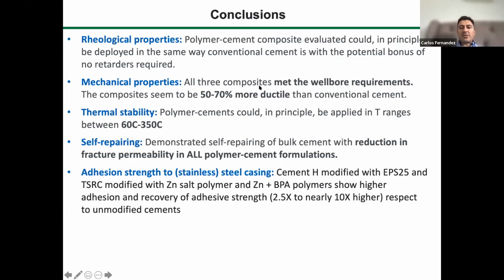Mechanical properties: the compressive strength is reduced, but still above the wellbore requirements. It's about 50 to 70% more ductile, and that's very important to reduce the fracture propagation rates and be able to self-heal. Or if the material doesn't self-heal, allow the cement to continue hydrating and fill those fractures before the fractures become detrimentally higher. The thermal stability, I haven't shown this, but the polymers are stable between 60 and 350 Celsius. There is one polymer formulation we haven't tried yet that is stable up to 420 Celsius. Like I say, there's still a lot of work to do.